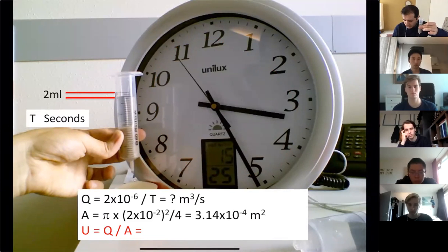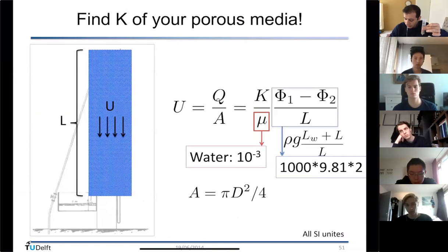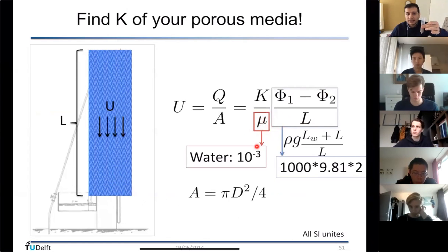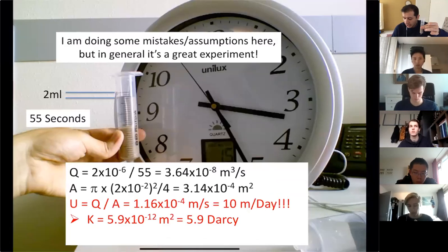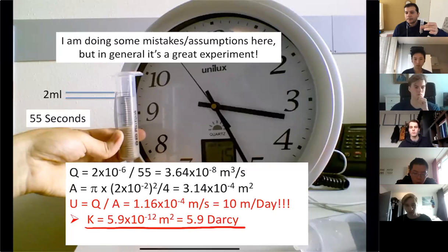Then I find the velocity based on Darcy's law. Q, the discharge rate, divided by the total cross-section area, is the velocity. I put the values here: potential difference, viscosity. These are all practical. We will practice this a lot this week. Then, based on the velocity that I have calculated, I find what the permeability should be, with potential difference, length, and all those things. Based on my calculations, I find permeability to be 6 Darcy, which is 5.9 times 10 to the power minus 12. One Darcy unit is 10 to the minus 12 square meter.